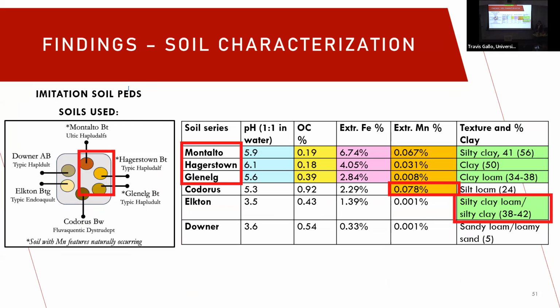For the soils where we had good coatings form, the pH of those soils, whoops, I thought I had those boxes highlighted, I'm sorry. The pHs of those soils tended to be above 5.5. And then the organic carbon content tended to be low, less than 0.4%. The extractable iron content was greater than 2.8%, and there appeared to be some need for manganese content of 0.008% or higher. And for all 3 samples where the manganese coatings formed well, the Montalto, Hagerstown, and Glenelg, they had higher clay contents of greater than 34%.